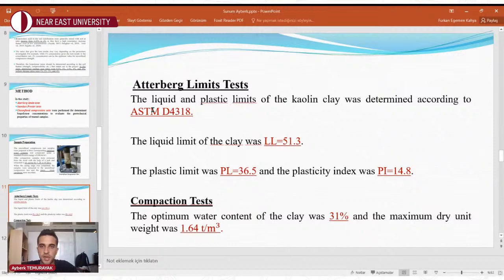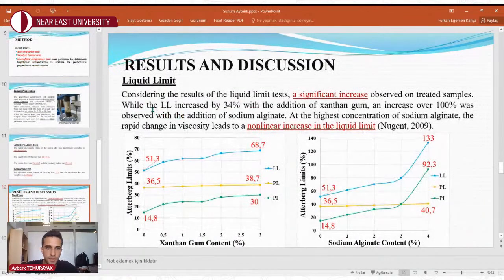The liquid and plastic limits of the kaolin clay were determined according to ASTM D4318. The liquid limit of the clay was 51.3 and plastic limit was 36.5 and the plasticity index was 14.8. The optimum water content of the clay was 31% and the maximum dry unit weight was 1.64 tons per cubic meter. Considering the results of the liquid limit tests, a significant increase was observed on treated samples. While the liquid limit increased by 34% with the addition of xanthan gum, from 51.3 to 68.7, there was an increase of over 100%, from 51.3 to 133, with the addition of sodium alginate. At the highest concentration of sodium alginate, the rapid change in viscosity leads to a nonlinear increase in the liquid limit.